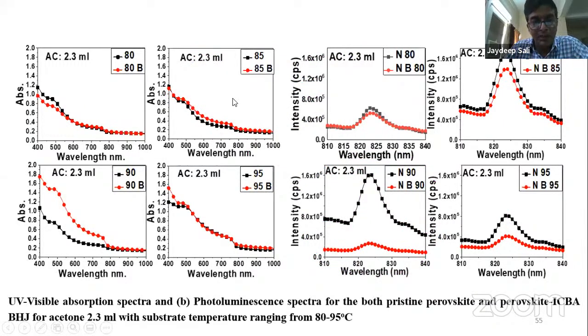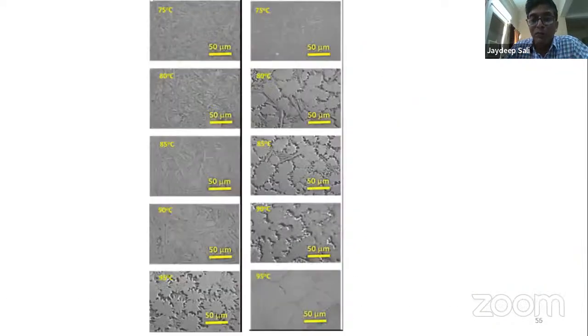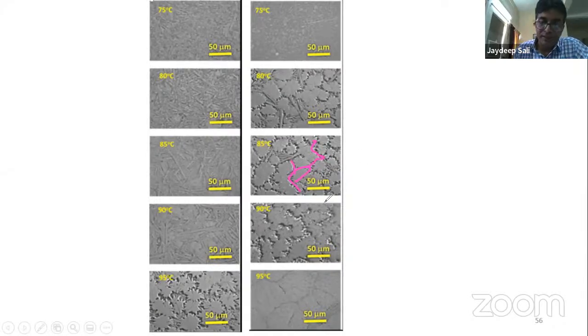Of course, this is still in a primary stage. Primary results have been published in a research journal, and more work is being done with some other solvent compositions. We have formed perovskite thin films with some other organic component, and here also it is clearly seen that the distribution of the second component at the grain boundaries can be controlled very precisely using the microemulsion scheme.